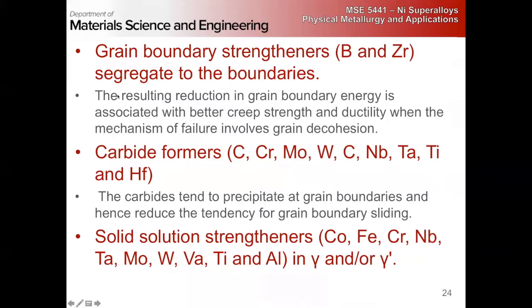Right. So if we could segregate our boron and zirconium to the grain boundaries, we lower our grain boundary energy, and we have better creep strength and ductility when we're going to have potential failure mechanisms that involve grain decohesion. Zirconium does form oxide. Generally, yeah, it's a mess. There's a lot of mechanisms going on here, right? These are kind of first order.